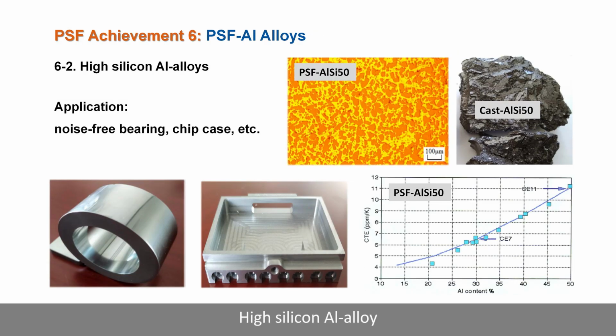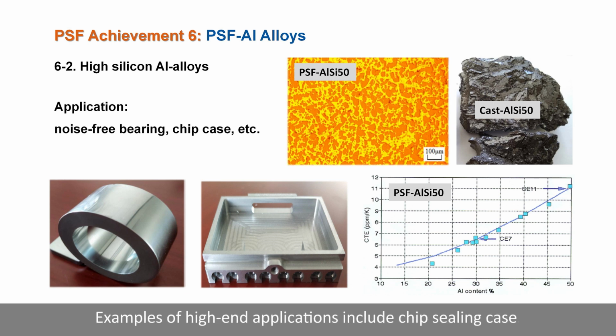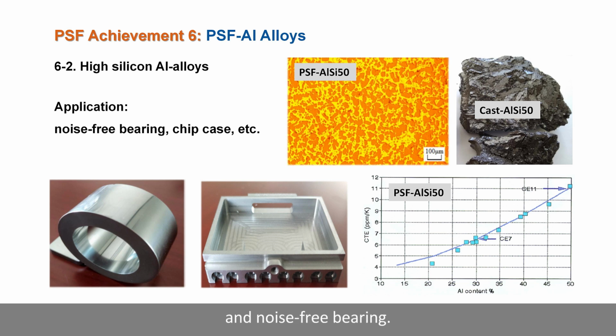High silicon alloy, which cannot be produced by traditional casting with more than 50% silicon, can be effectively made by PSF. You can see that the primary silicon phase is very evenly and finely distributed, compared to the very rough and brittle as-cast structure. Examples of high-end applications include chip sealing case and noise-free bearing.